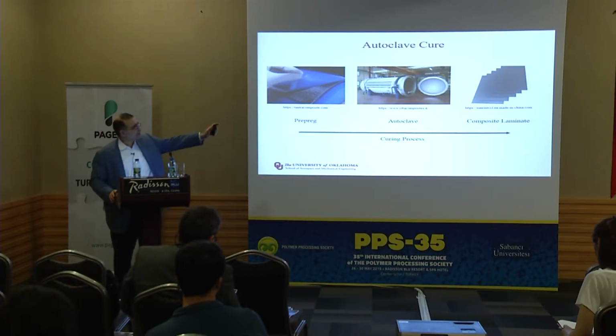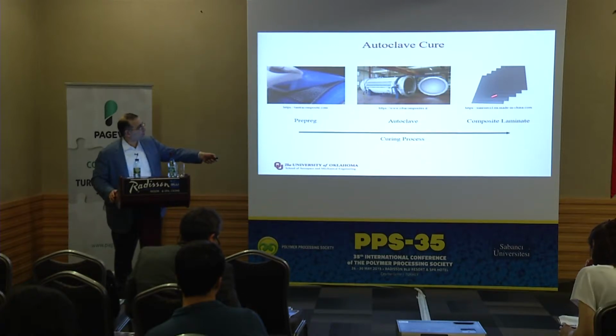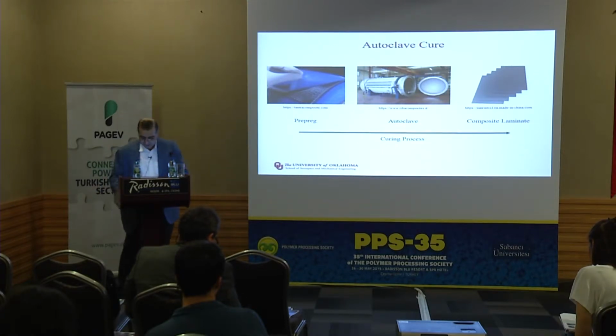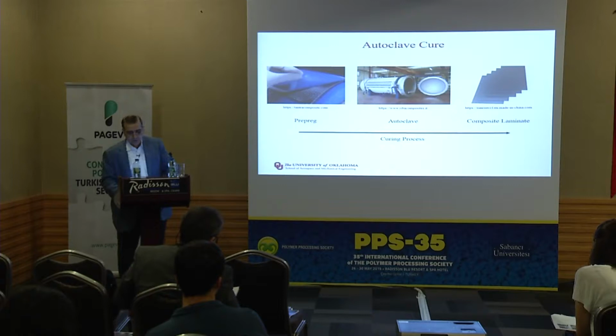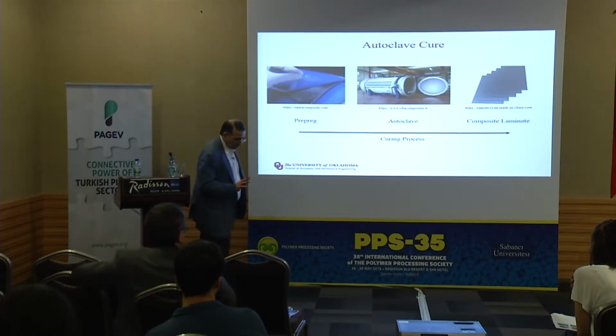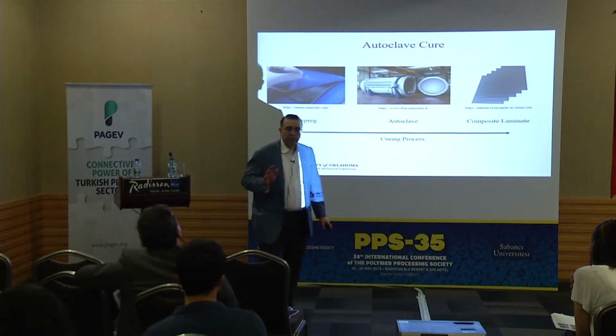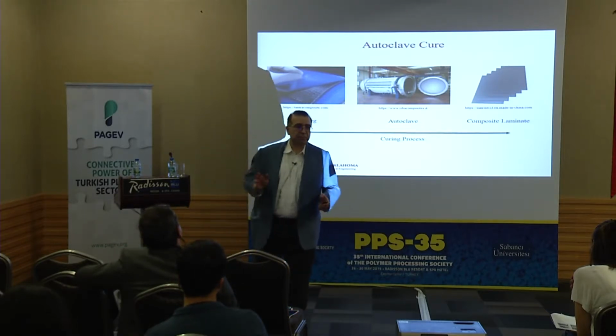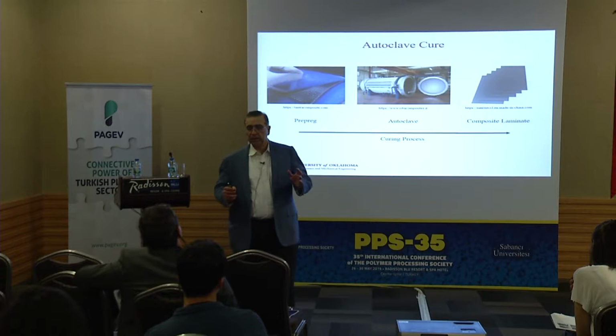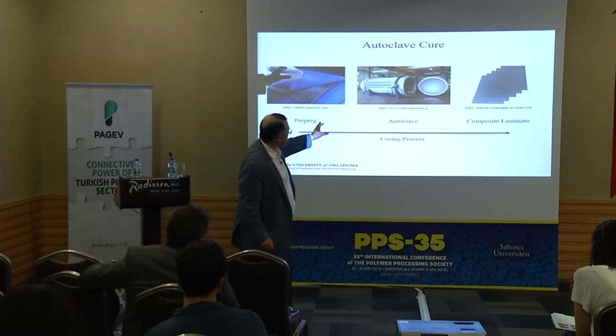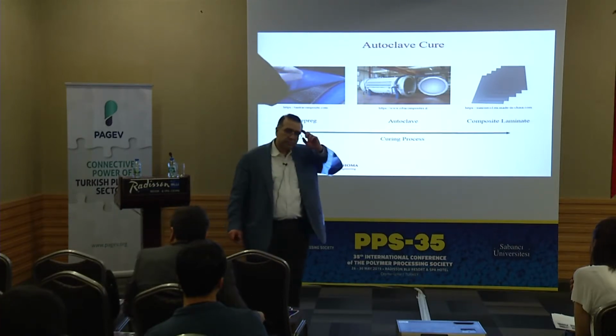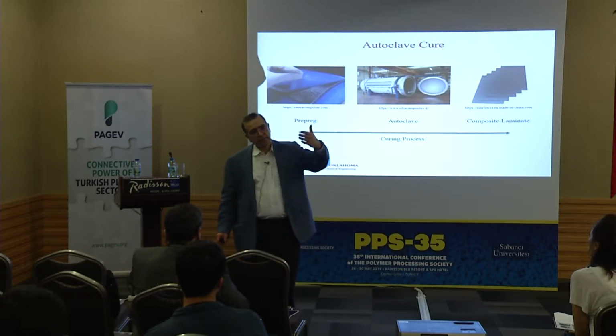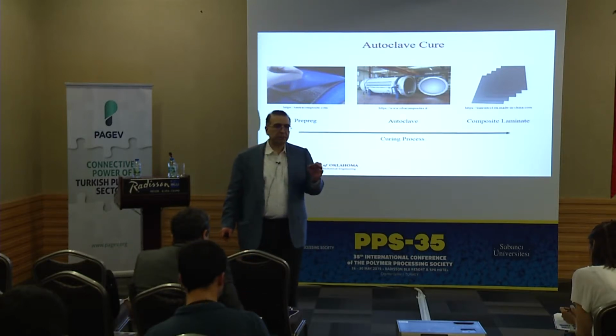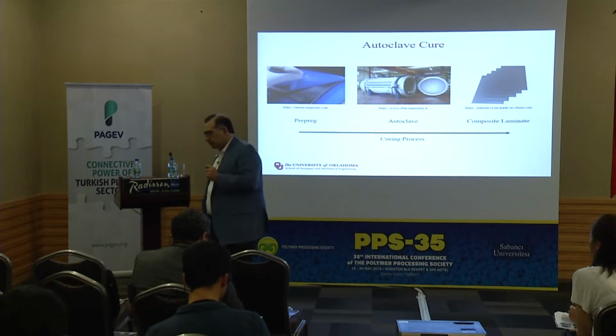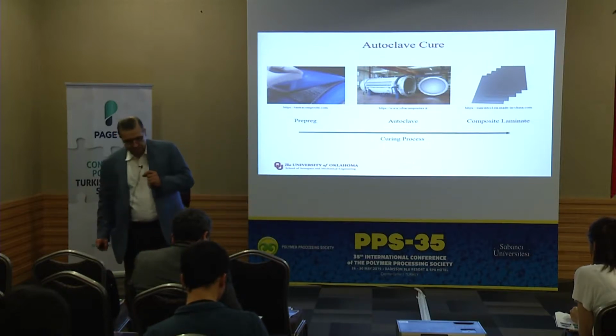The highest fiber content you'll get, very likely, will be using these prepregs and using an autoclave. Now, I will tell you the pressure and the temperature range. Okay? The pressure range in autoclaves: many composite parts would be processed under 100 psi.